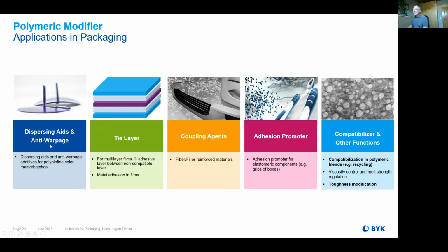They can work as dispersants, and beside that, they can also reduce warpage. That might be interesting for color masterbatch, especially for closures. And beside that, this modifier can be used as tie layers, so for multilayer films to improve the adhesion between incompatible materials, or it will increase the metal adhesion in film applications. Beside that, it can work as a coupling agent for fiber fillers and works as a reinforcing material. It might also be used as an adhesion promoter for elastomeric components, for example, here for toothbrushes or grips of boxes, something like that. And one very interesting part, especially for recycling, is the compatibilization.